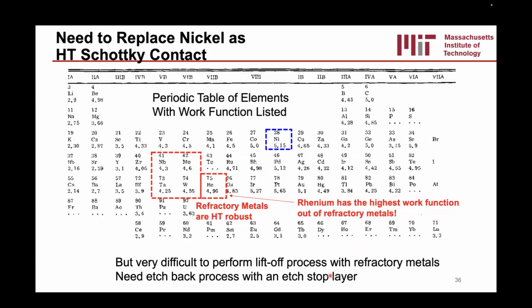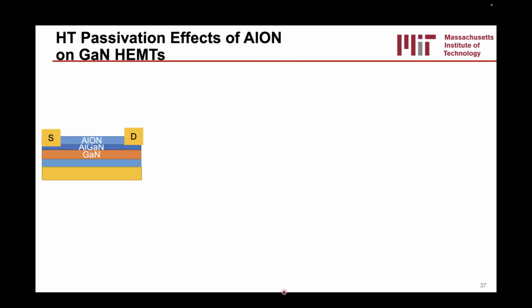It's very difficult to do a lift-off process because the temperatures typically needed to evaporate these materials will often burn the resist, especially things like PMMA, for instance. And so we had to develop an etch back process where we etch a via and sputter the rhenium. And so to do that, we needed to develop an etch stop layer to have a robust process. So that's what we did.